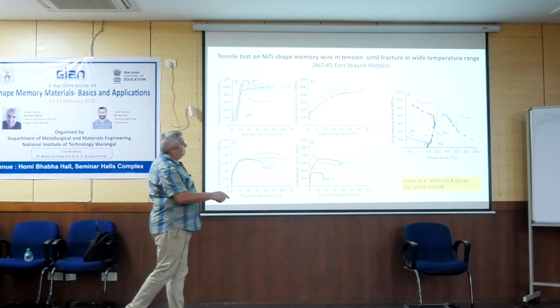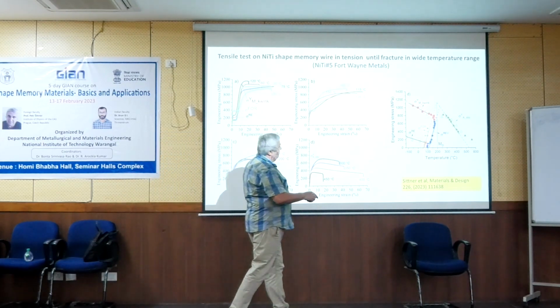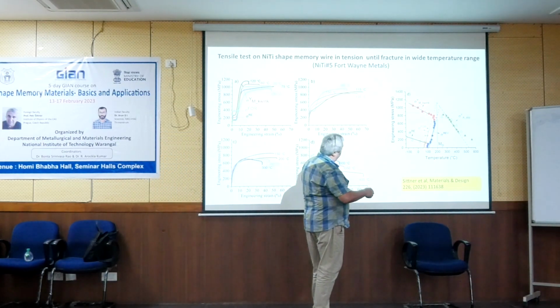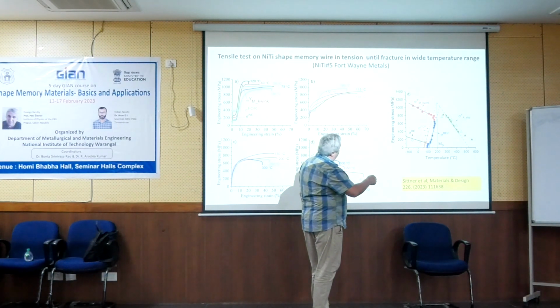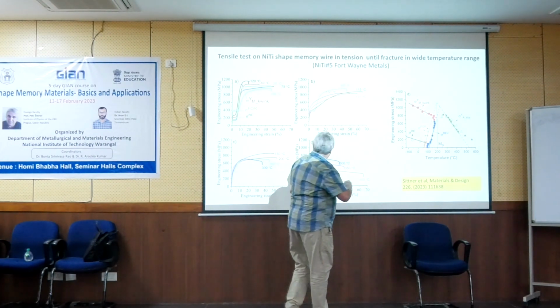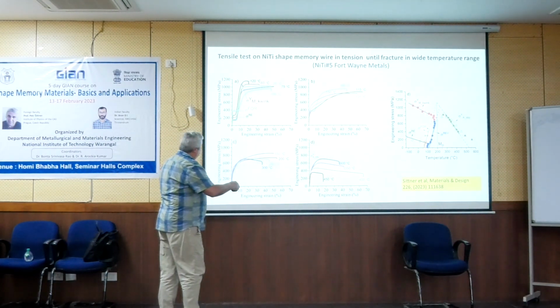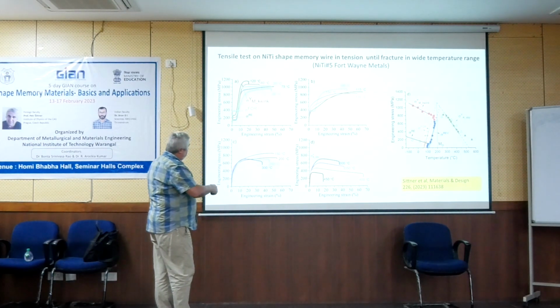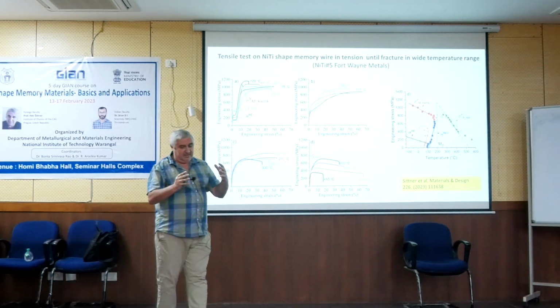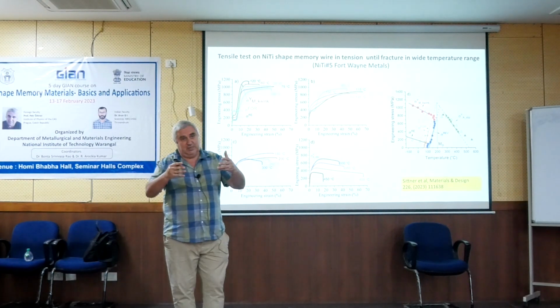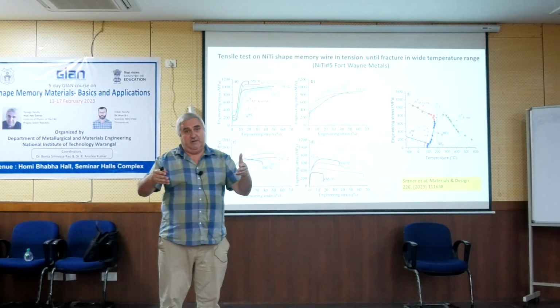So if you look at this diagram, here this is the stress for inducing the transformation. Here you are in the martensite state, and then between 150 and 300, you have some kind of transition range where, as I said, the martensite which is induced immediately deforms plastically.